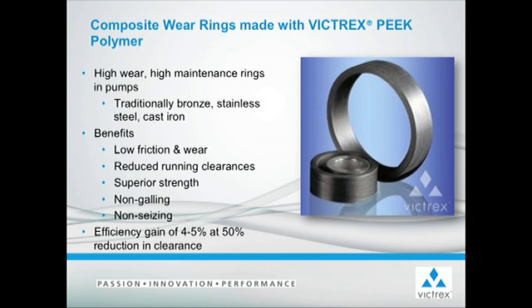Another application are composite wear rings made with VICTREX PEEK Polymer. These are high wear, high maintenance rings that are in pumps, traditionally made from bronze, stainless steel, and cast iron. And the benefits of PEEK are its low friction and wear, the ability to have lower and reduced running clearances, its superior strength and stiffness. It's a non-galling material and also non-seizing, and offers an efficiency gain of 4 to 5% at a 50% reduction in clearance.